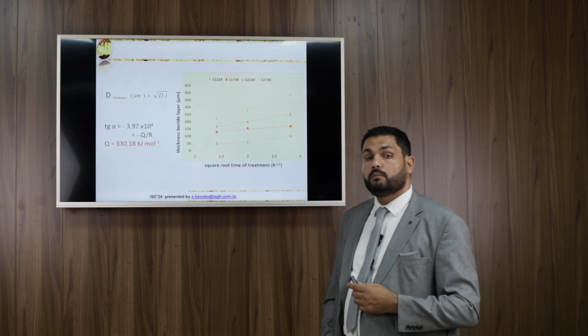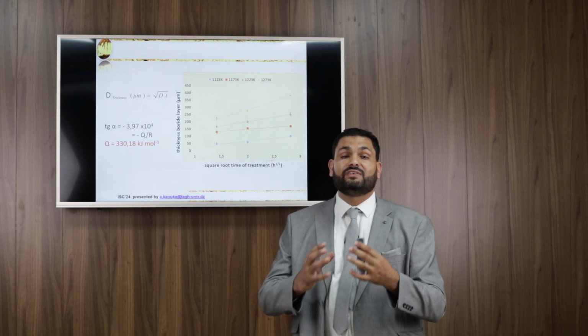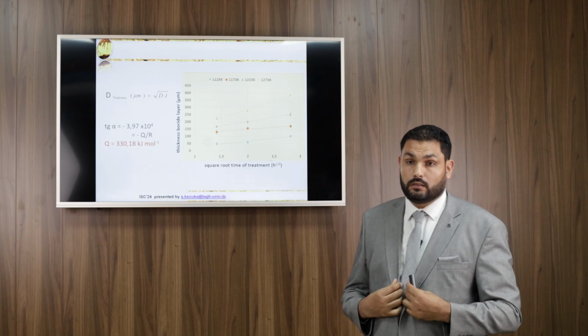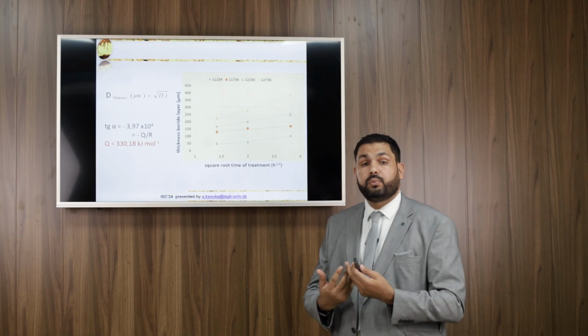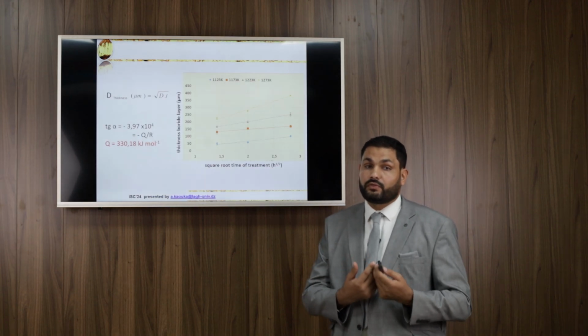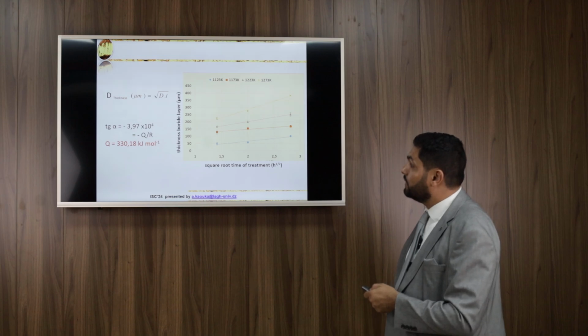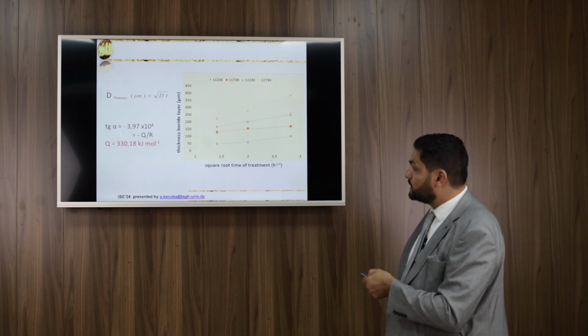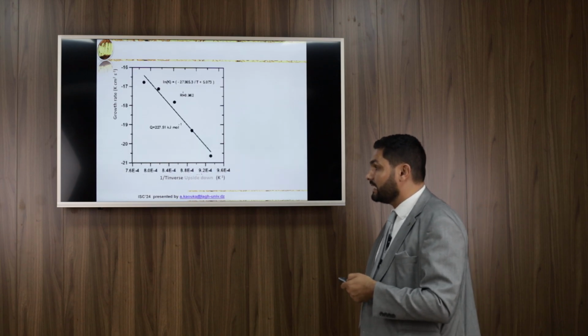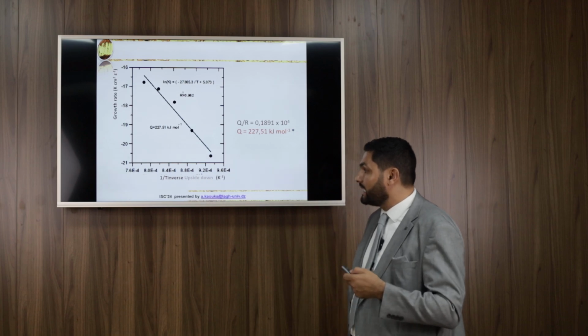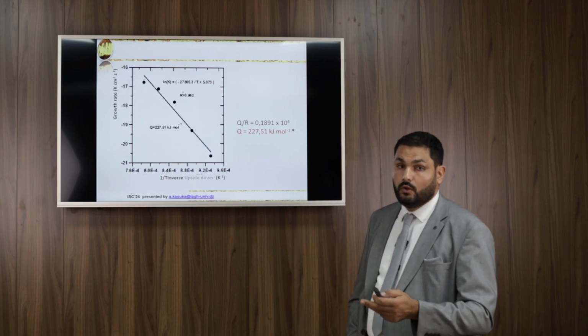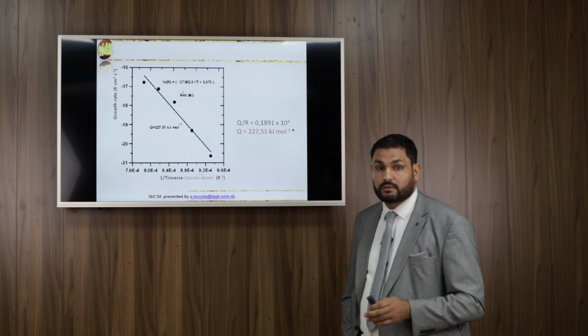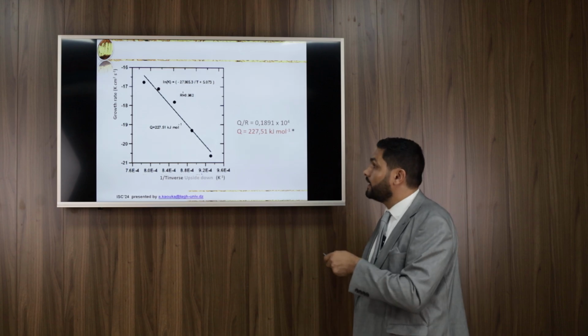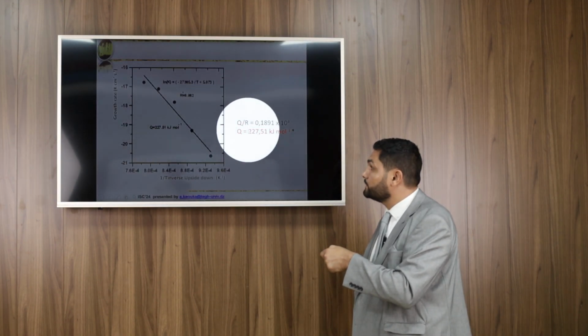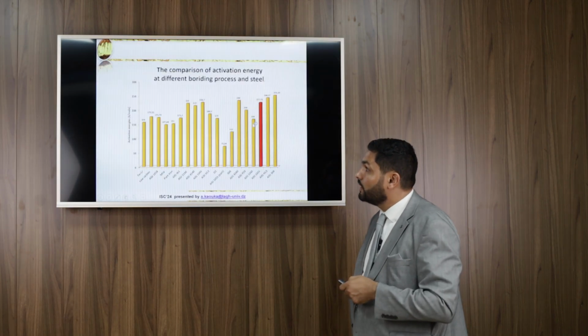We can also calculate the diffusion of boride layers, and the most important result is to calculate the activation energy to create the boride layers on the substrate. So we have found an important activation energy, about 330 kilojoules per mole. After that, we try to measure the growth rate as a function of the inverse of temperature, to measure also the activation energy, and we found relatively the same value. It's about 227 kilojoules per mole.